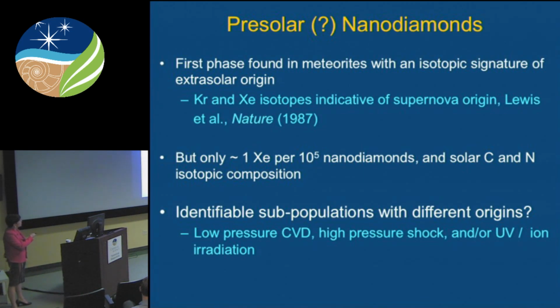So let's talk about diamond now. As I mentioned earlier, the pre-solar nanodiamonds are a really important phase in cosmochemistry because this is the first phase found in meteorites with the isotopic signature indicative of the extrasolar origin. And there's a paper in Nature in 1987 by Lewis et al. that showed that the krypton and xenon isotopes in these residues measured in bulk show these nucleosynthetic anomalies that are indicative of a supernova origin. But in fact, there's only one xenon atom for every 10 to the 5th nanodiamonds or so.